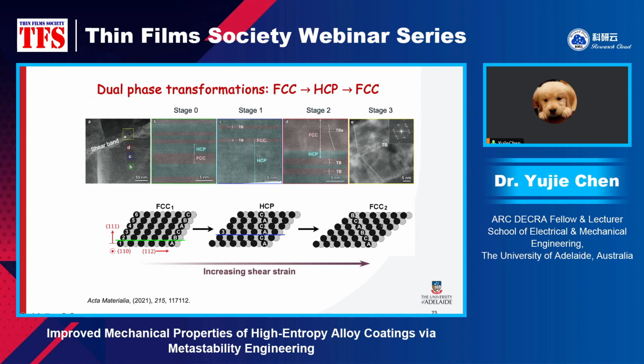What is the benefit of dual phase transformation? We know that a single step phase transformation produces 35% plastic strain, but dual phase transformation will produce 70% plastic strain, which has been doubled. Right? That means the material's ability to absorb strain energy has been significantly increased. So that's a reason why this coating shows such a high strength and at the same time shows large plasticity, because it can deform plastically.